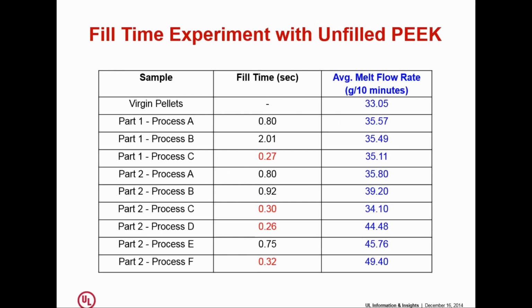This is a study we did a number of years ago with a company that was being badgered by their customer to slow down the injection speed because they were, quote unquote, harming the material, and the material they were molding was PEEK. If you're degrading a material with too much shear, there's a real easy way to tell. Just run a melt flow rate test on your raw material and then on the molded parts. And if the molded part melt flow rate is much higher than that of the pellets, then yes, you're doing some damage.